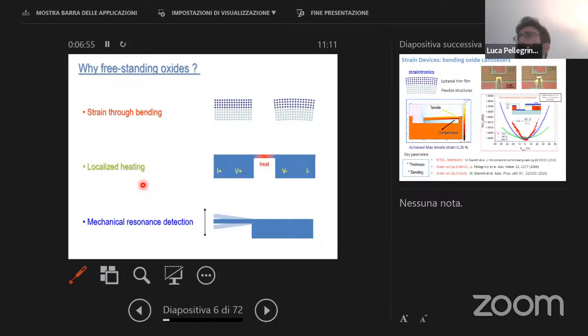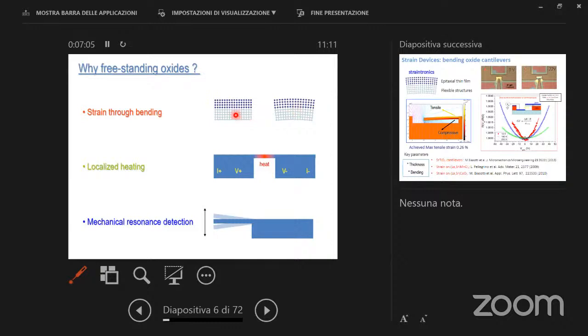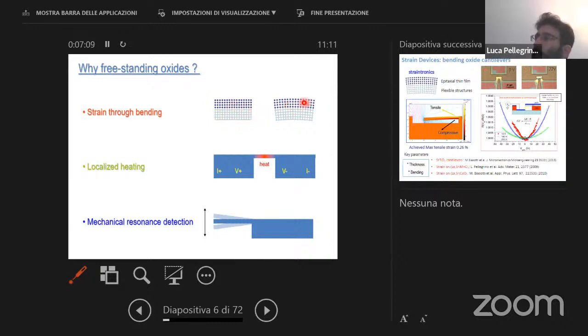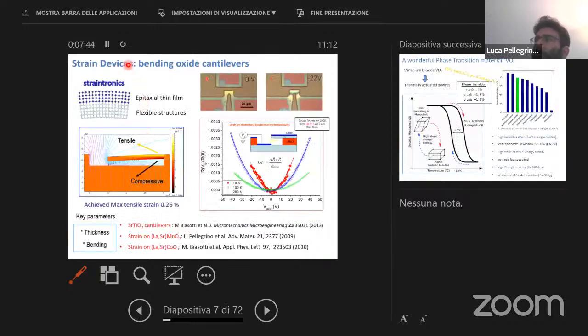Okay, so why use freestanding oxide? We have three types of experiments in mind. One is the strain bending. If you have, for example, a crystalline structure, we can bend it and we can apply strain. We can have localized heating by flowing current into the freestanding structure. The freestanding structure does not exchange heat with the environment easily as clamped films, because you do not have the heat conduction through the substrate. So you can heat up a lot with a small amount of energy. And then we are studying also what happens if we are moving the structure and we are detecting the resonance frequencies of our microstructures. So the first example is strain devices through bending.